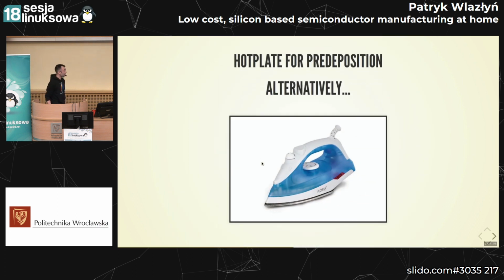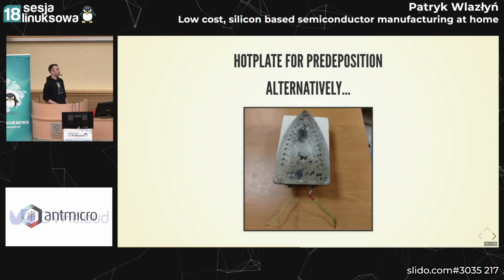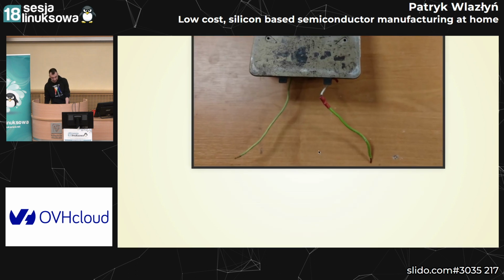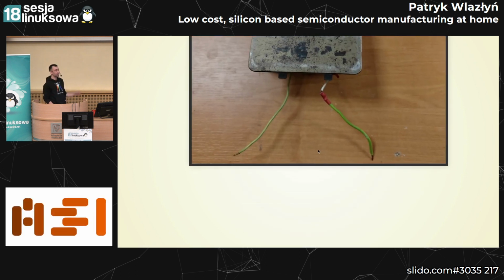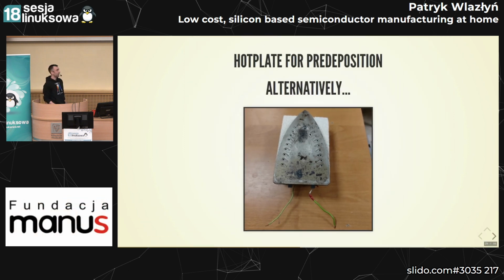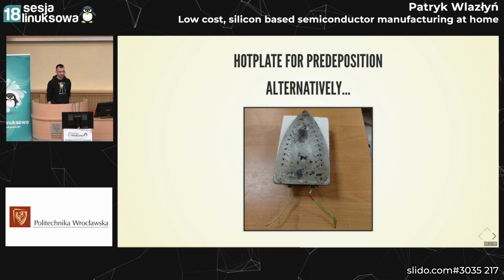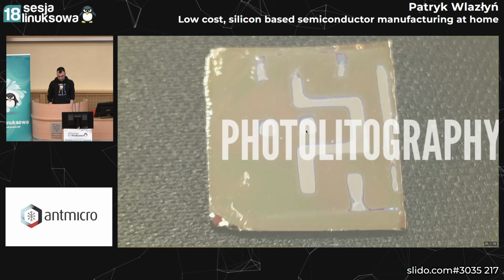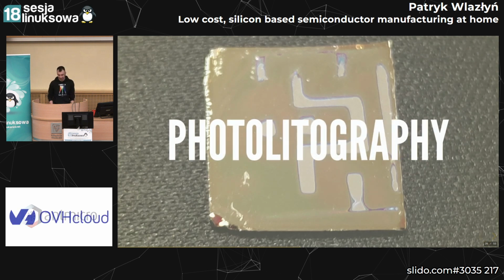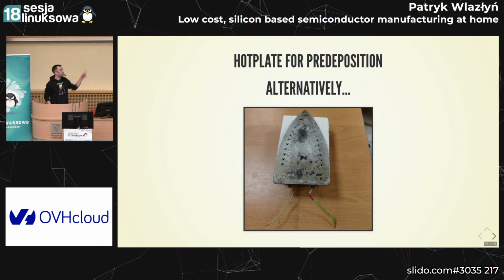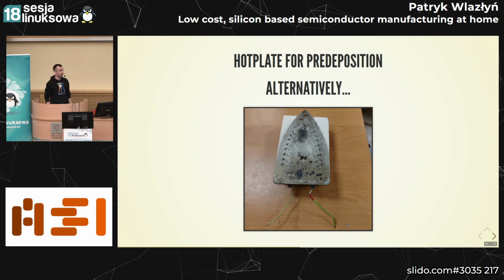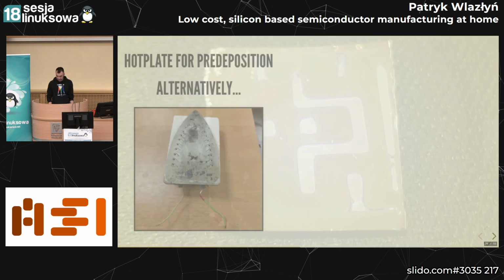Alternatively, this is how we started: you take an iron and take off the part that gets hot, and you take these two cables, connect them to the Raspberry Pi through the SSR, and you can drive with pulse width modulation how much you heat. And we were able to make a working MOSFET using this technique. It's actually cheap if you find some old iron sitting somewhere. Although the hot plate works a little bit better. You don't have the temperature sensing here, so we actually use the infrared camera to check how hot it is.